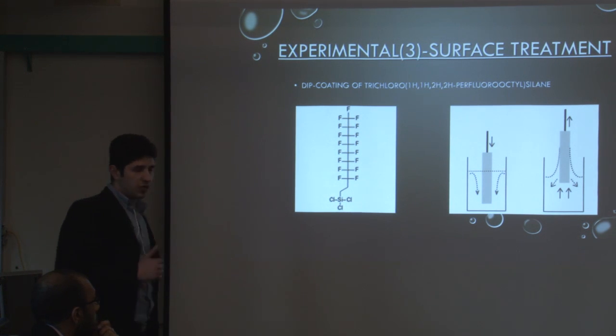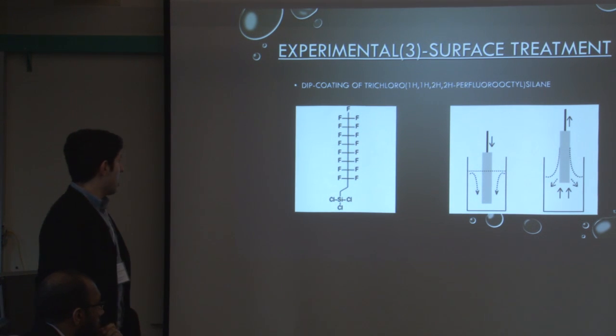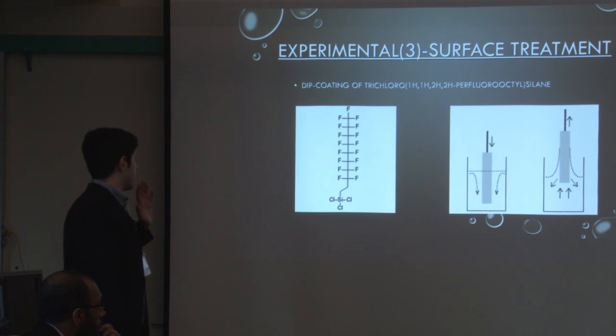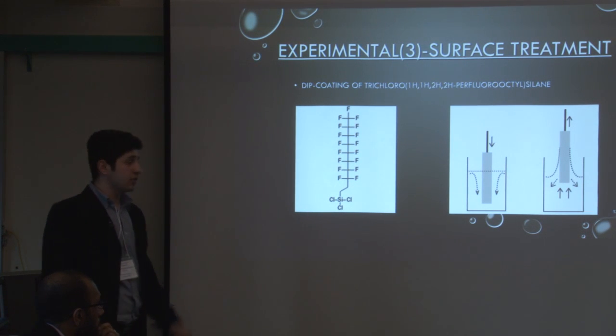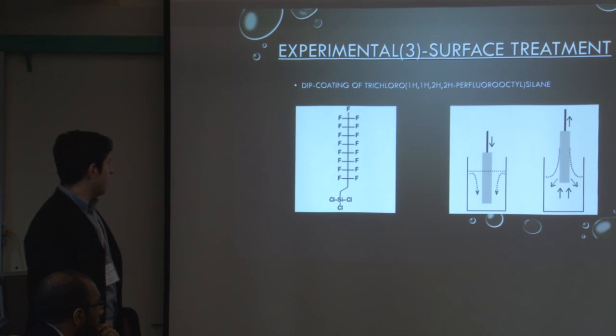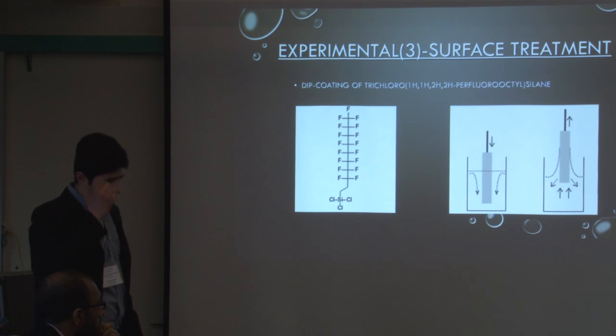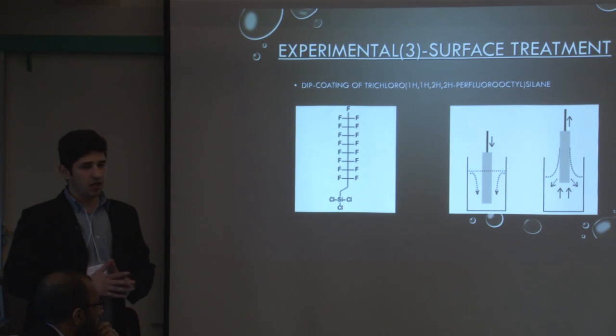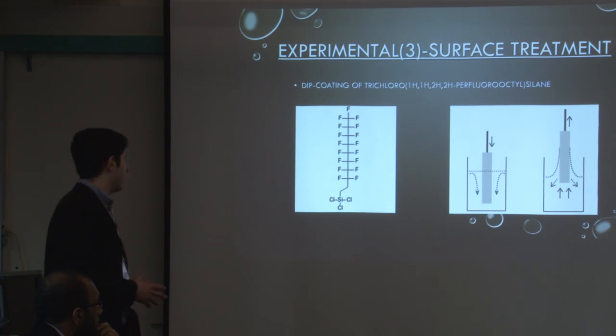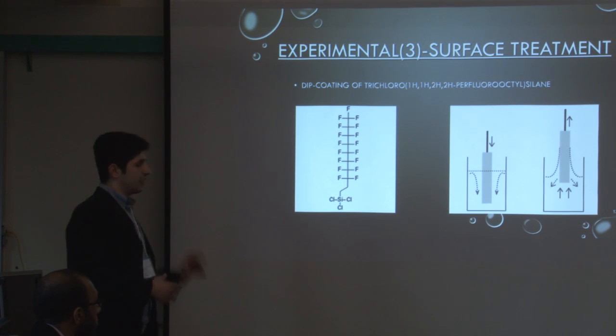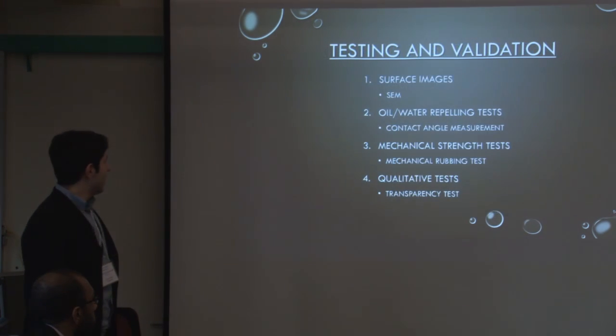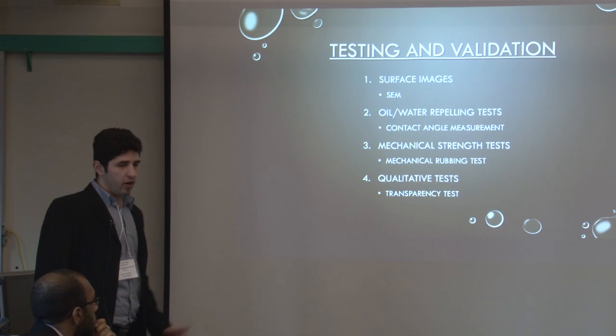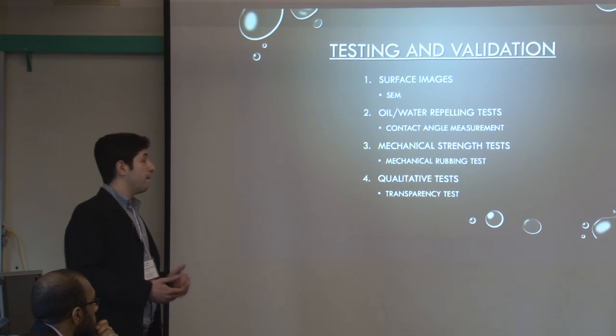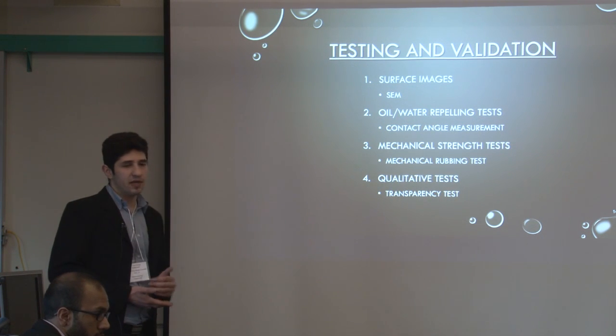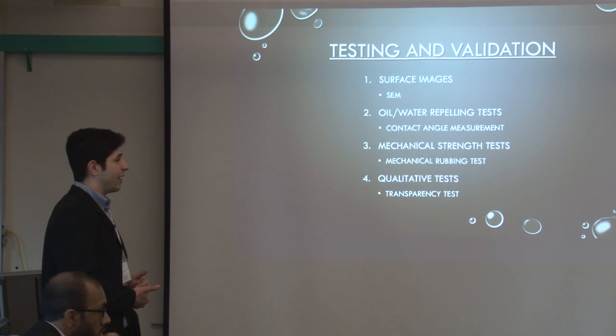The next step was to reinforce the hydrophobicity of the surface. We introduced a very low surface energy material, a silane material which has a long carbon chain with fluorines attached to it. It was a dip coating process, and we did that several times until the surface was fully coated with the silane compound. Now we have to go back and check whether our design meets the customer requirements or the hypothesis that we made at the beginning.